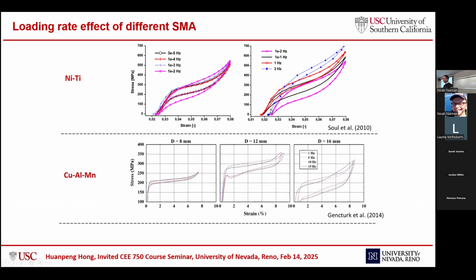And copper aluminum manganese alloy is very stable. When the loading rate is up to 15 Hertz, the hysteresis loop has very little or negligible change. The research on the strain rate effect of nickel titanium cobalt is still underway. I'm expecting this material to behave very similar to nickel titanium alloy.